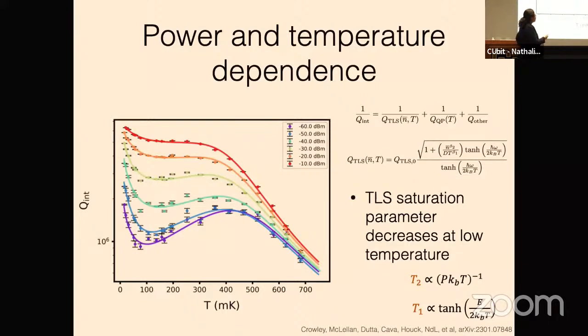And the nice thing about this is that what we can extract is something that we're calling here Q_TLS naught, which is a prefactor on the TLS related loss. And that now feels a lot like a material parameter, right? Because you now have something that is basically just the linear absorption associated with TLSs. And I can now take that and use it as a basis for comparison across many devices.